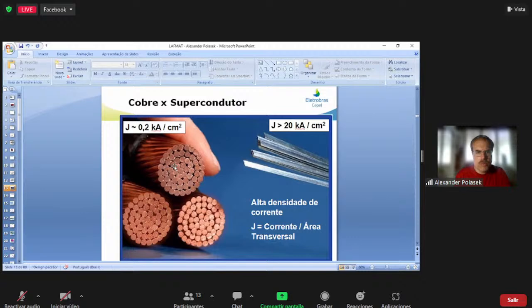coils for machines or equipment, which typically have 200 amps per square centimeter, whereas typical superconductors for applications can achieve much higher current density. This is not the superconductor density. This is density considering all the material, because you see here you have a metallic coating. The superconductor is just a part of the material, as I told you. If you consider the whole cross-section, you can still achieve tens of kiloamps. So you have 100, 200 times more current density. It means you can have much more compact and lighter equipment and devices, and it brings a lot of advantages.